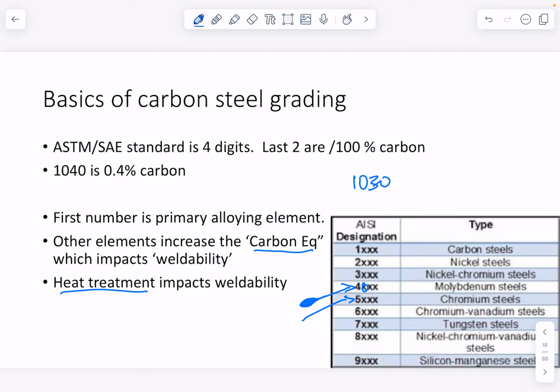The heat treatment also impacts on your weldability. So if I get a fully annealed piece of 4140, I can probably comfortably run a bead of weld along that. If it's got a volume of thickness to it, I might want to preheat it a little bit to stop the quench at the weld pool. But that'll weld and it'll be okay. However, if that 4140 has been heat treated, then I am asking for it to fail if I weld on it without doing a lot of preparation, both pre and post. So again, just keep in mind that welding is fairly straightforward, but there's a lot of fine detail and complexity in it.